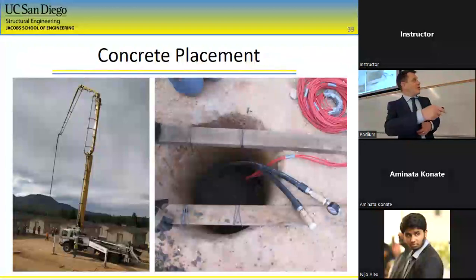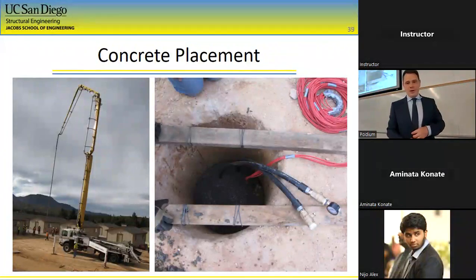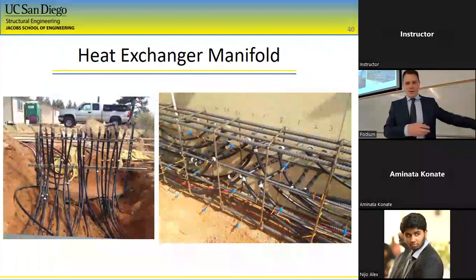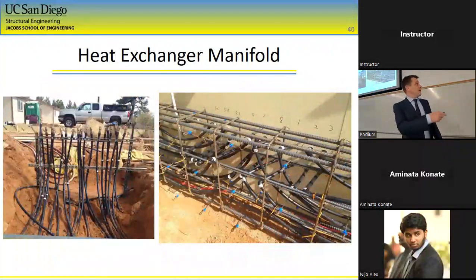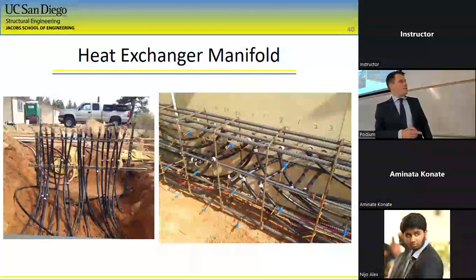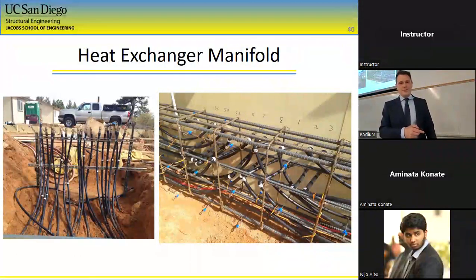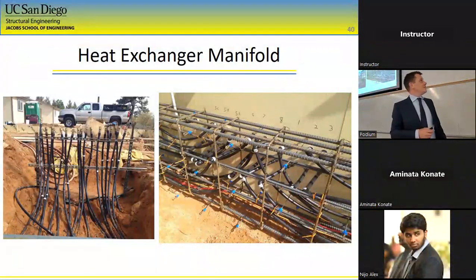So this is the dry hole. You can see that it stays open very well through this material. We had vibrating wire strain gauges at different depths, and our heating pipes. And then we tremied the concrete from the bottom up. And then we had to route all of the pipes into our manifold. It's very good that we took this picture here because you can see that the pipes from each of the foundations came in different orders. So we had 1, 2, 3, 5, 6, 7.